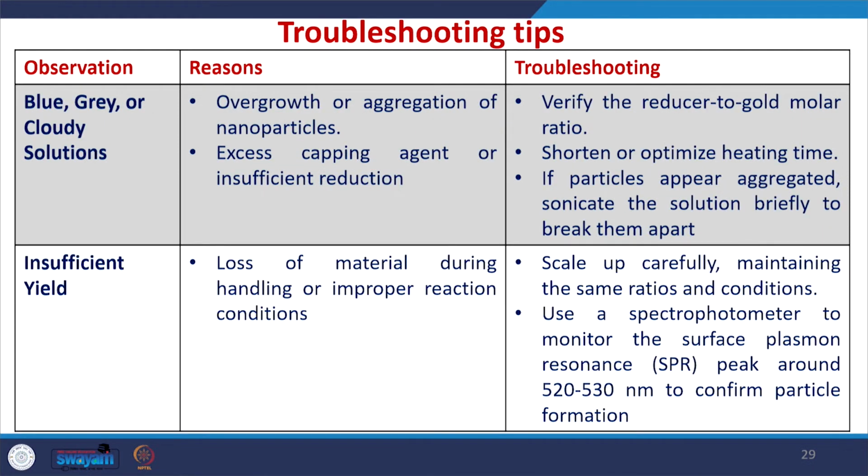Some of the other observations are, if you are getting a blue, grey or cloudy solution, it may be due to the overgrowth or aggregation of nanoparticles, or it may be due to excess capping agent or insufficient reduction. So, check the reducer to gold molar ratio and also shorten or optimize the heating time. If the particles appear aggregated, sonicate the solution briefly to break them apart.